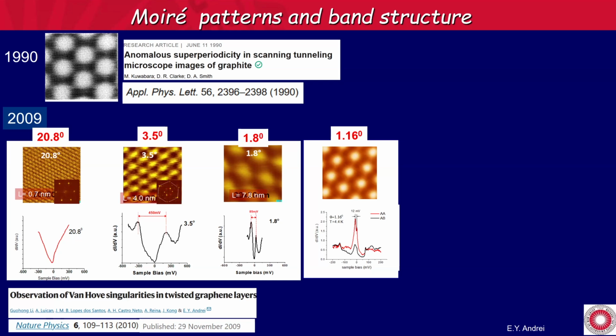And to our surprise, we were looking for something totally different. We were looking for Landau levels and all sorts of other things. To our surprise, we saw these patterns, and it turned out that in that sample, we had many, many different twist angles. And when we looked at the band structure, which nobody thought of looking at before, we saw that as you decrease the twist angle, the band structure is reconstructed. So you go down to 3.5 degrees, you see the Van Hove singularities pop out. They're 450 millivolts apart. At 1.8 degrees, they get closer. And at 1.16, they actually overlapped. And it looked like we created a charge density wave. It looked like we have a little gap here in this flat band.